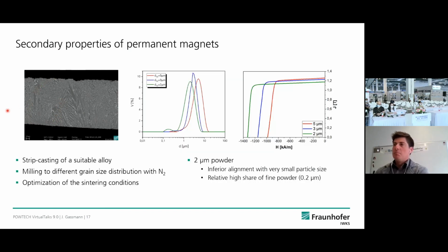So after the strip casting, a milling procedure follows. We milled the material to particle sizes of 2 to 5 micrometers. The smaller we milled, the higher the amount of fines in our product in this case. So it is well known that with changing grain size, magnetic properties also change. Smaller particles show a higher coercivity. However, it's also harder to align them, therefore remanence is decreasing.